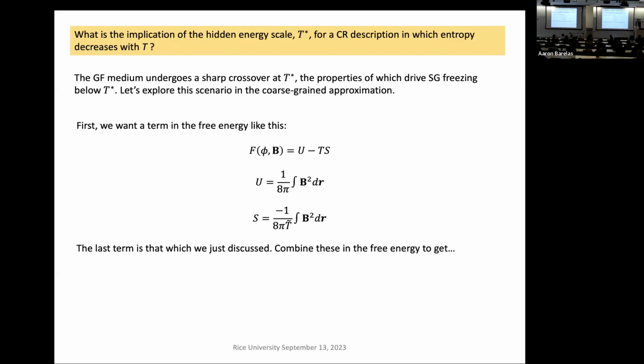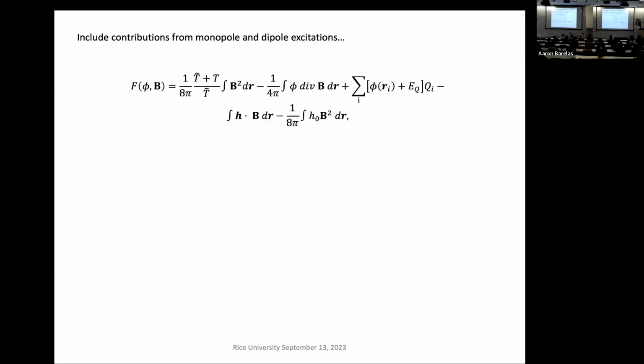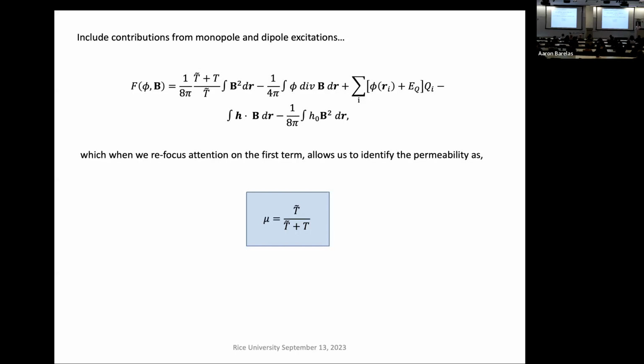Okay. So what's the implication? Hidden energy scale. If we write out the free energy, for the undergrads, F equals U minus TS, right? Everybody knows that. So we have the internal energy through the B field and the entropy that we just discussed, and we find the free energy. We put in a whole bunch of other terms. Forget about these terms. These are just terms required for a Gaussian field. Let's focus on this one. This comes from the U minus TS. That term leads to a permeability that's temperature dependent. If anyone knows of a system where permeability is temperature dependent, please tell me. But it makes perfect sense because we know the interaction is being mediated by a bunch of spins whose behavior is temperature dependent, right? So it makes sense that the permeability is temperature dependent. But I believe this is the only instantiation in all of physics of this effect.